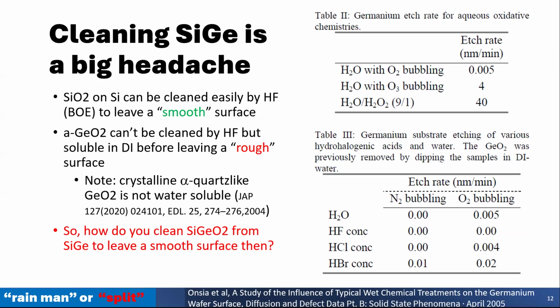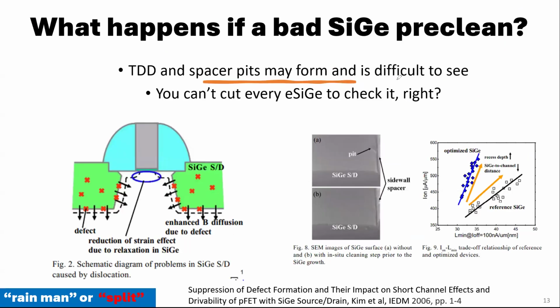Okay. So what happens if a bad SiGe pre-clean is done? So you say, okay, forget it, I can't do a perfect pre-clean. So what? So what is here? For example, the SiGe source and drain. If you don't clean these edges off, the spacer here, the edges off, you will form pits. Okay. And that's going to hurt your device because you need to have a perfect crystalline structure in your SiGe. And you cannot have that with the pits.